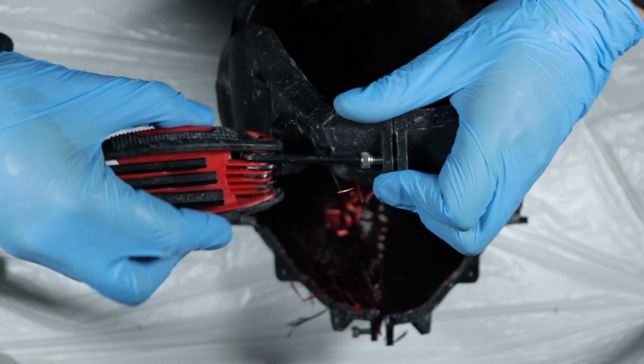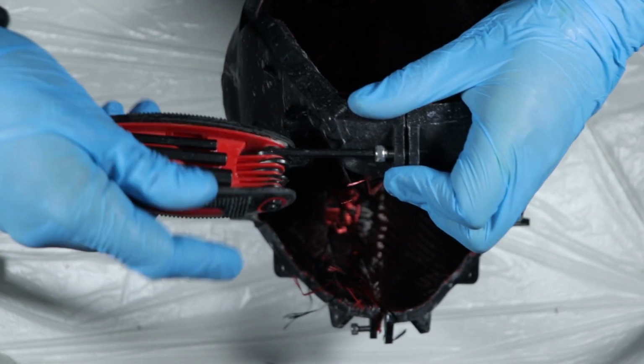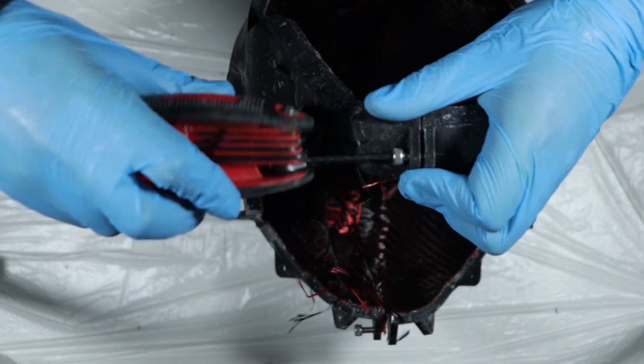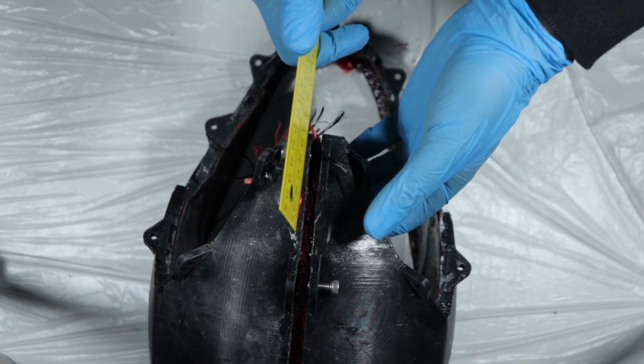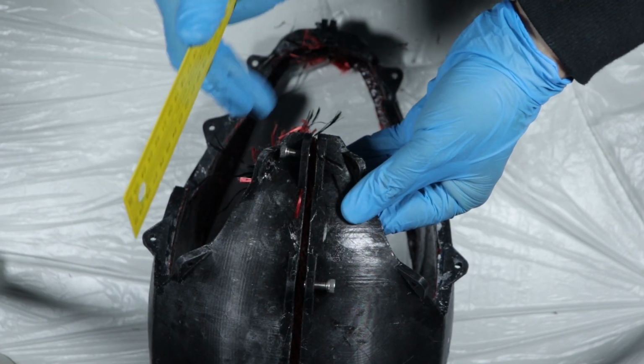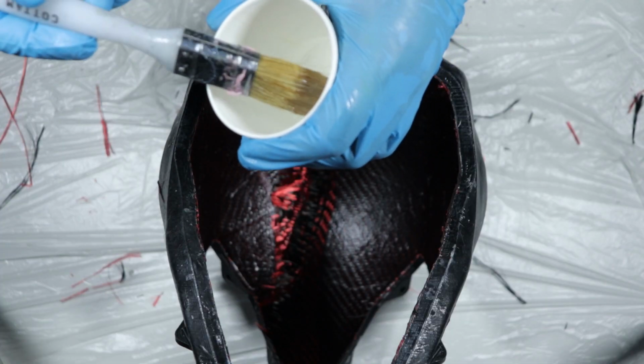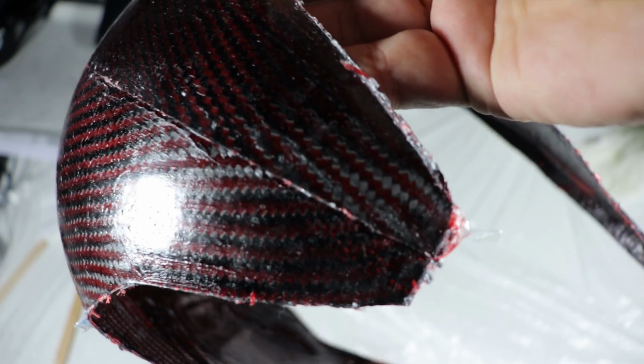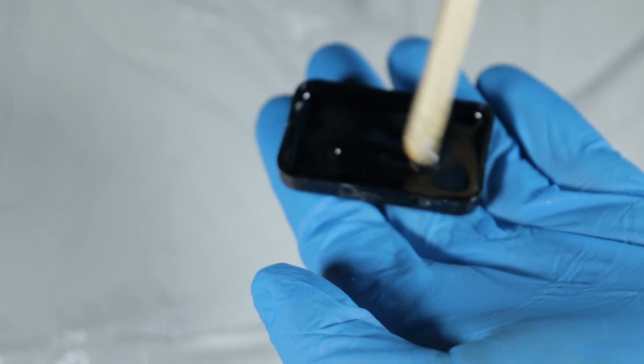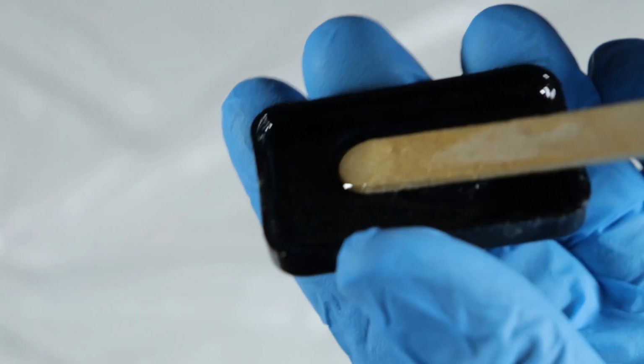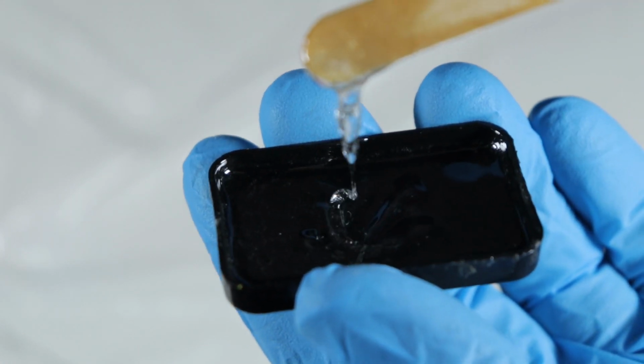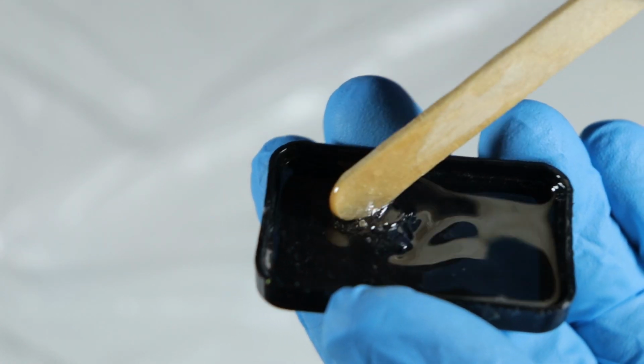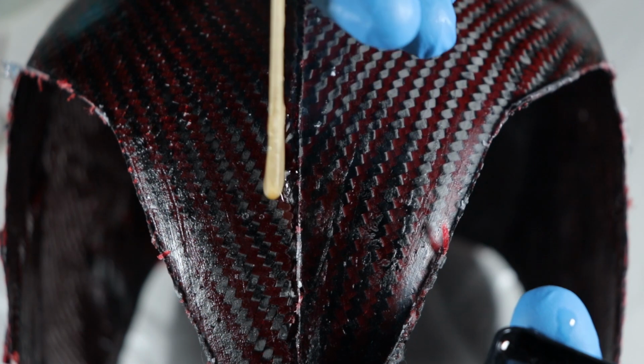Here, you can see the two halves of the mold ready to be assembled. Assembling them is very simple. The only thing you need to worry about is to avoid having the fabric stuck between the two halves of the mold. And it looks like I should have added more epoxy resin, but that's okay. I mix a fast curing hardener and epoxy resin and left it for around 10 to 15 minutes until the epoxy resin is very viscous. I'm using a simple wood stick and applied resin.